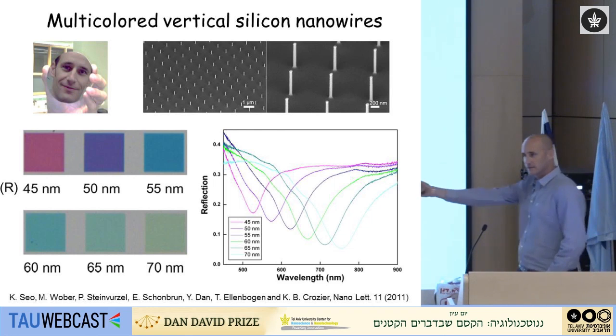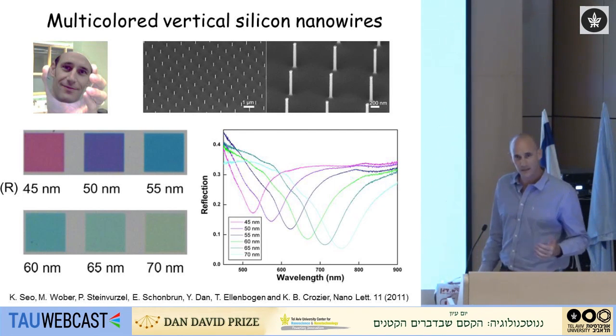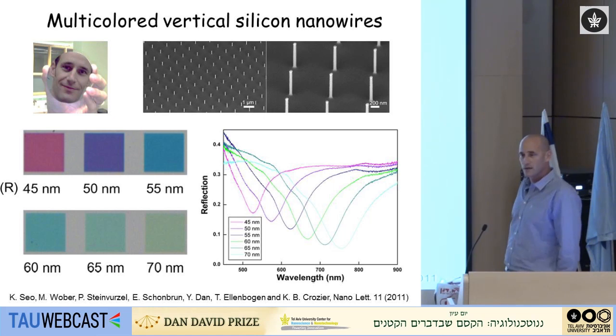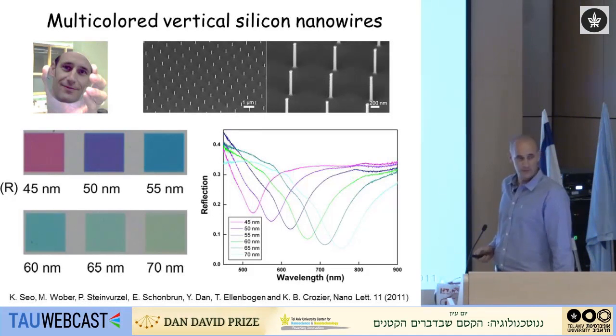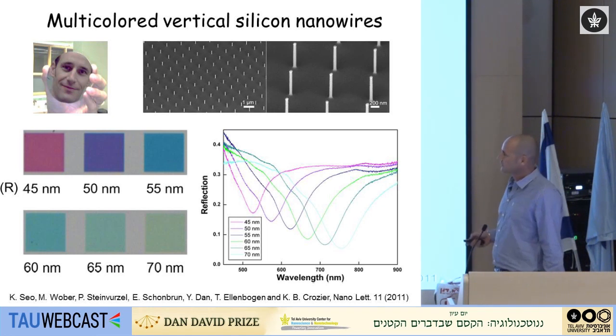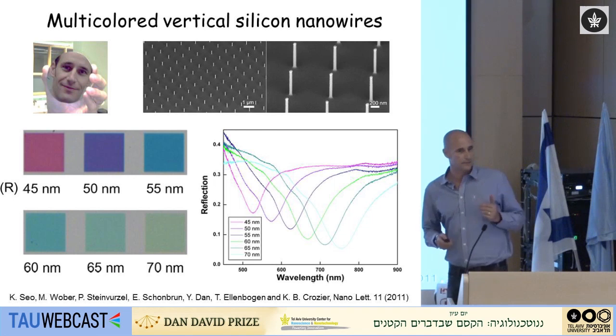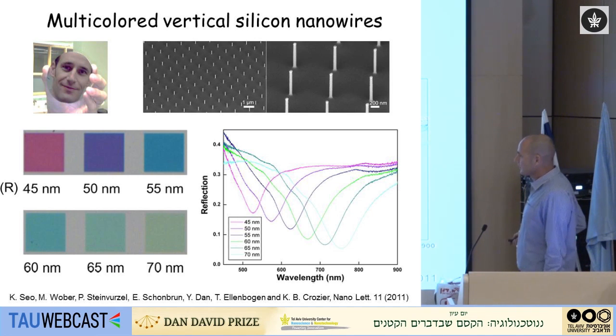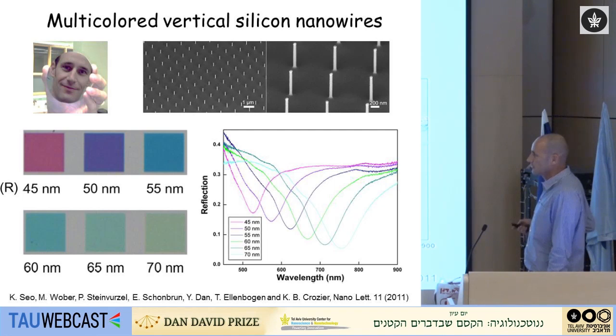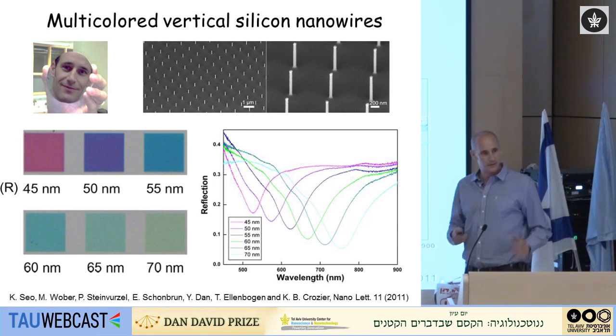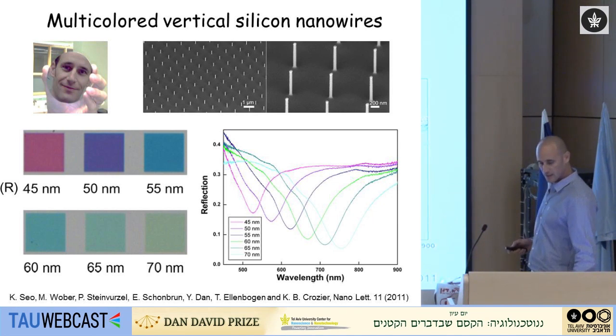Here you see my face reflected off a silicon wafer. Silicon is a gray material and it is highly reflective. However, if you nanostructure it and create nanowires on top of the silicon, made also from silicon, it was shown a few years back that you get very unusual optical effects. Suddenly, silicon starts to take color, and the color is highly dependent on the radius of the nanowire — changing the radius just a bit takes you to a completely different color. When you measure the reflection spectra, each sample corresponds to a single dip, and you can tune the position of this dip by tuning the radius of the nanowire.